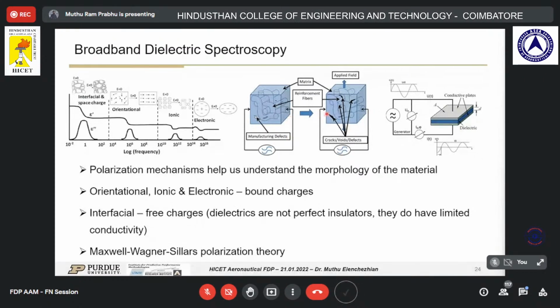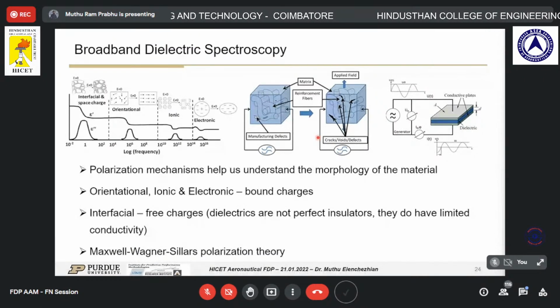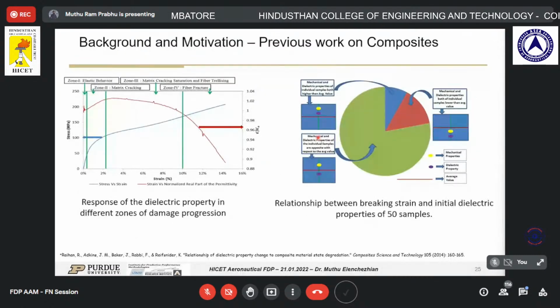Based on how the property changes between the initial state and the later state, the difference between them is obtained. The relationship between the final state of the structure versus the initial state is what will be correlated to other patterns. This technique is not very popular, but it has been developing. My research group, which I worked with earlier at UT Arlington, has been developing this a lot, and based on this we did a lot of work.